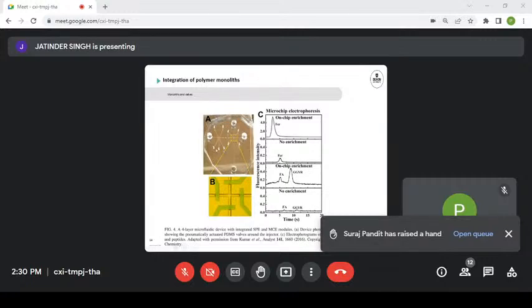So solid phase extraction happened here, could load the sample, have a waste, do an elution. All the channels here were for the solid phase extraction. With the valve here closed, there was no interaction with our separation system, no contamination. And only once we opened the valves that are sitting here, it was possible to electrophoretically elute the solid phase extraction phase onto the intersection and then do a cross injection and a separation. So a much higher level of integration, because we've got both the porous material, the stationary phase for solid phase extraction, and the valves here for fluidic control.